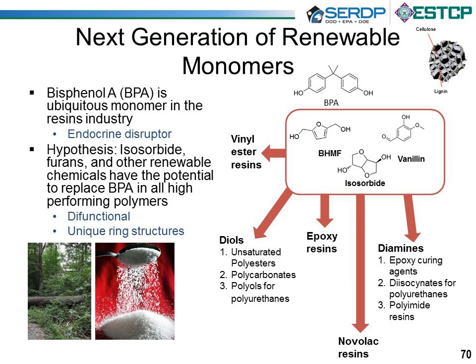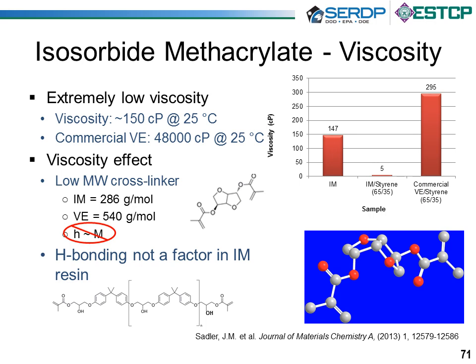One of the first things we made was this isosorbide methacrylate, which you can see the molecule in the center of the page. It's a fairly small molecule, compact, relative to that of the vinyl ester crosslinker itself, and it has a much lower viscosity. The viscosity of it, as shown in the graph on the top right, is only 150 centipoise compared to that of a vinyl ester crosslinker with a viscosity of about 50,000 centipoise. So orders of magnitude lower viscosity.